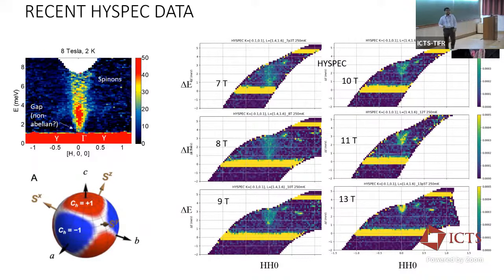So there is a progressive change. If you are coming from the high field side to the low field side, and we are applying a field along H parallel to A, it's almost like you have a magnon mode which slowly melts and forms this continuum of scattering right around 8 Tesla. And this is pretty remarkable that we see that.